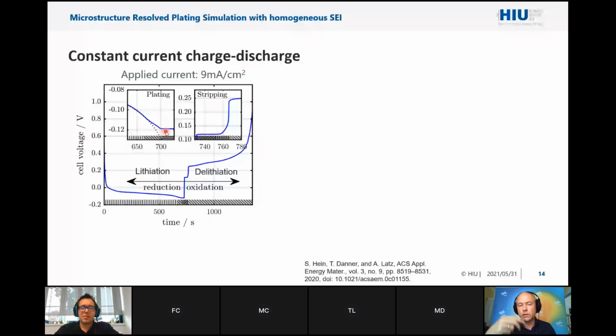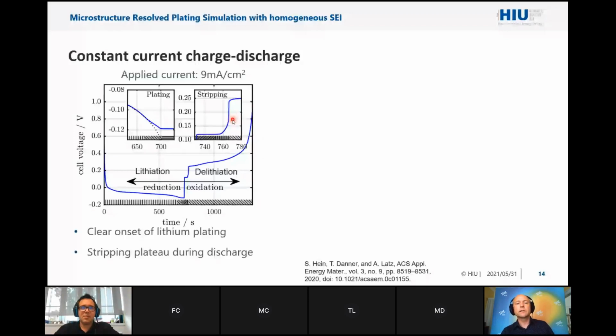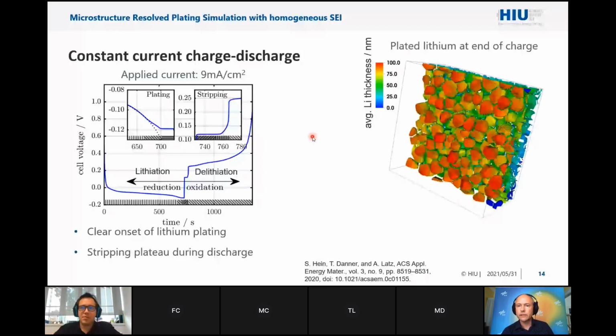If you go in the delithiation, so the oxidation regime, you do stripping, deintercalation of the anode, you find the stripping plateau, which is sometimes used as an indicator for plating. And then at this point, all the lithium is resolved, and you find again the OCV or the voltage of the graphite. And here is what you see at the end, the plated lithium at the end of charge. You see that again, it's mostly at the separator, but it's also not homogeneous. Some particles are covered by a thick plating film, some only by a relatively thin plating film, in the nanometer regime.